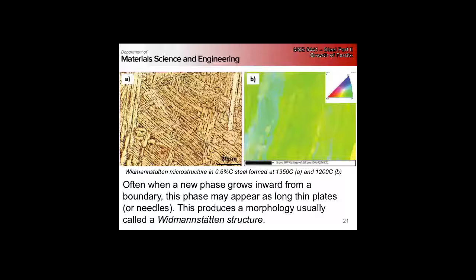They're growing - can you sort of think of what the potential mechanism is? Where are these nucleating? At the boundaries. And we already said that both the cementite, proeutectoid cementite, and proeutectoid ferrite nucleate with a preferential orientation relationship. So it's going to have an orientation relationship at that interface and maintains it as we go out.